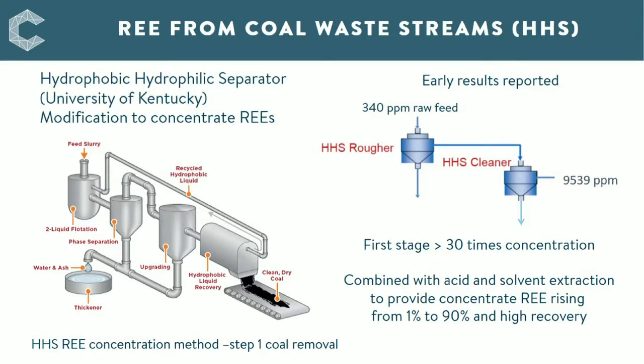The first method is aimed primarily at elements in tailings ponds, although it could be adapted for a range of coal wastes. There are really two stages, and this slide looks at the first part of that, to remove the carbon from the mineral resource. And this diagram shows a hydrophobic hydrophilic separation system. An organic solvent is used to concentrate carbon-containing material, and this leaves finely divided mineral waste, which would have previously been discarded, but now, of course, contains rare earth elements.